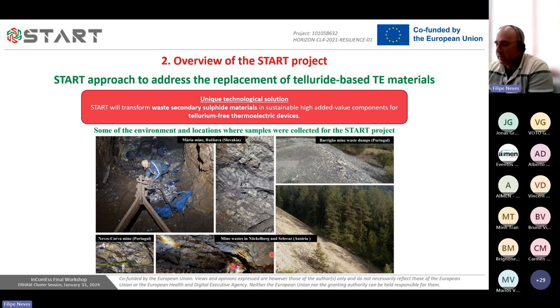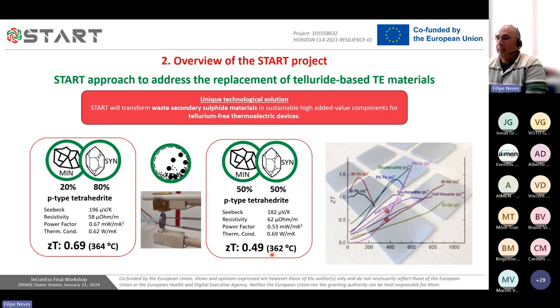After collecting the mineral, it implies the treatment and the incorporation of this mineral, which is being conducted mainly to process the thermoelectric elements by powder technology. We have already mixed the mineral with different amounts of synthetic tetrahedrite. For example, here are some of the thermoelectrical properties for two different samples with different ratios of minerals with the synthetic material, 20-80 and 50-50, and we can see here the figure of merit that is highlighted for these two different samples.